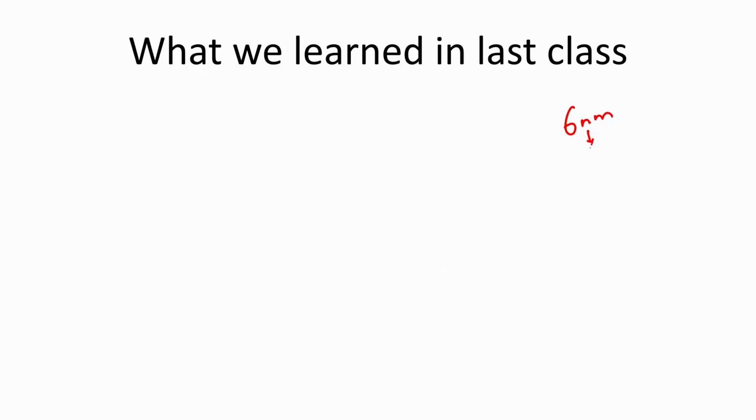If it is a spherical particle, there is a certain size range that we want. If we want it to sustainably flow in the blood vessel or remain in our body, we want it to be greater than 6 nanometer, because 6 nanometer is essentially the kidney filtration. If we want it to be injectable in, let us say, blood vessels, then we want it to be less than 5 micron, because the smallest vessels that we have are close to about 5-6 microns.